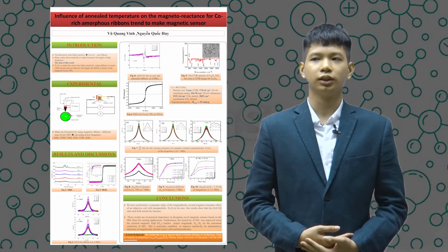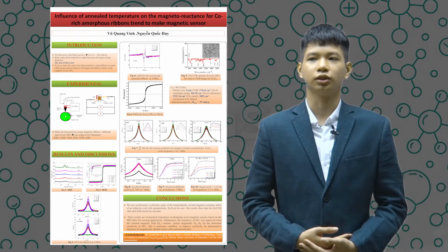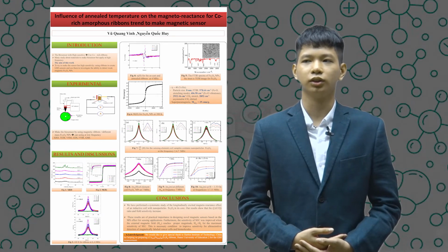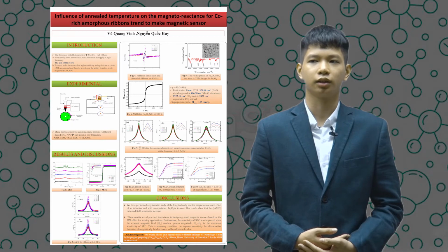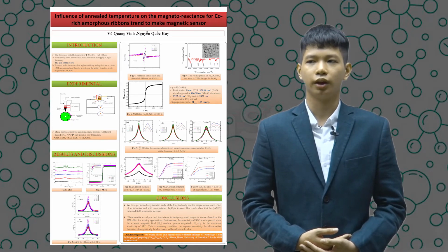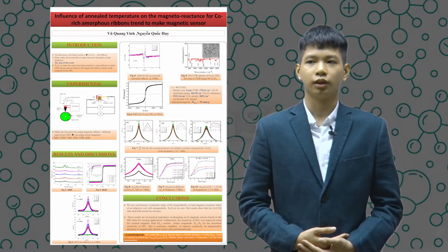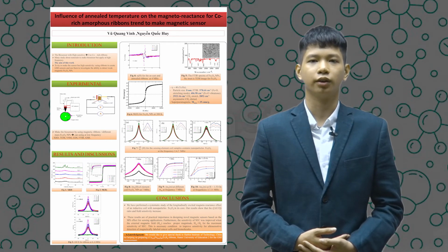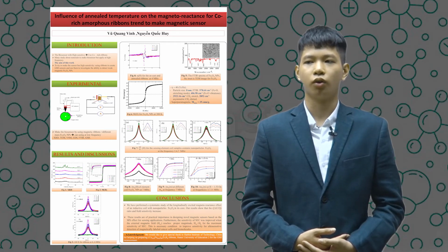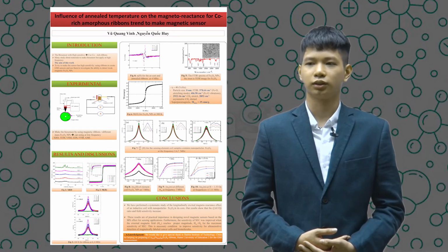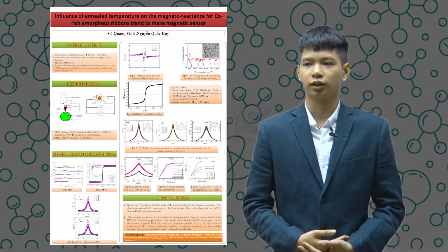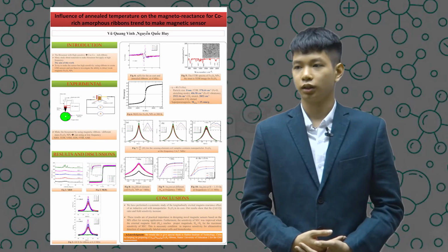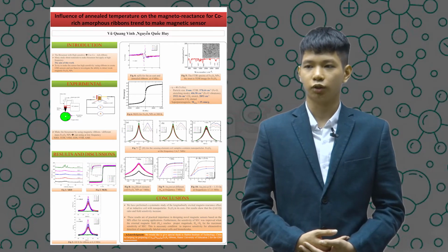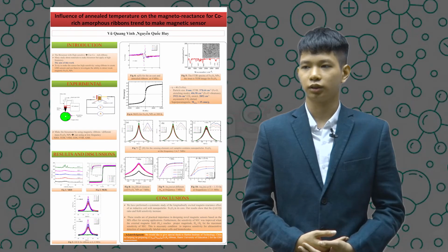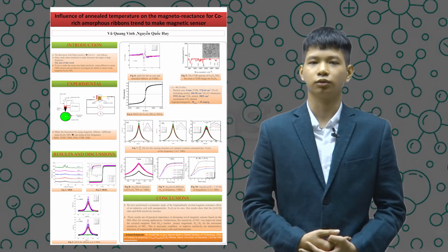The main results are discussed now. Fig 1 shows XRD patterns of as-quenched and annealed ribbons. Ribbons were annealed at different temperatures from 100 to 600 degrees C. All samples are amorphous except the sample annealed at 600 degrees C. In the curve some peaks appear, which means the sample was crystallized.